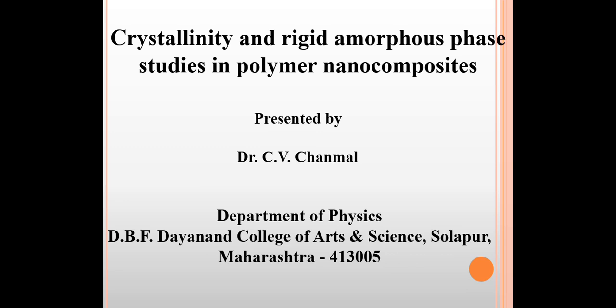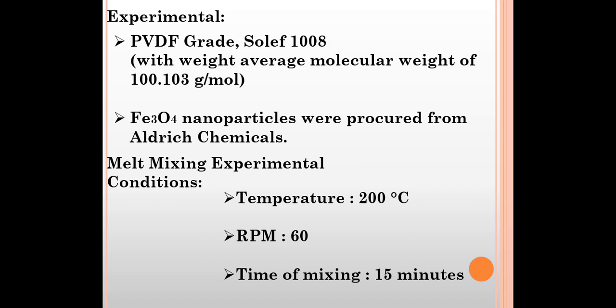The title of my presentation is Crystallinity and Rigid Amorphous Phase Studies in Polymer Nanocomposites. The materials that I am using in my work are a PVDF polymer, which is a well-known ferroelectric polymer, and magnetic nanoparticles. The nanoparticle is Fe3O4. I am preparing my nanocomposite by a simple melt mixing technique.